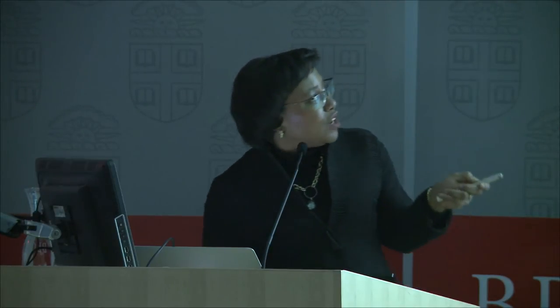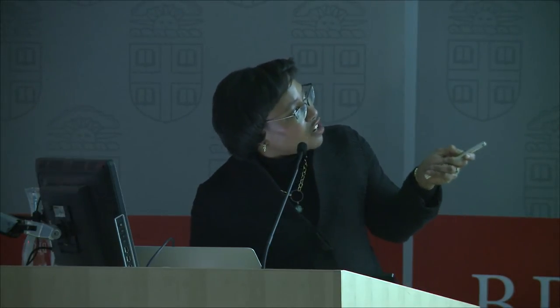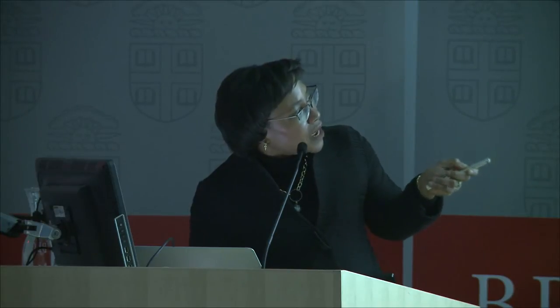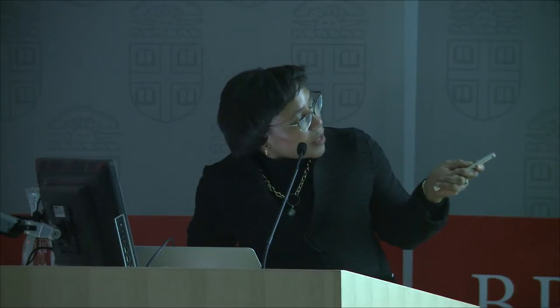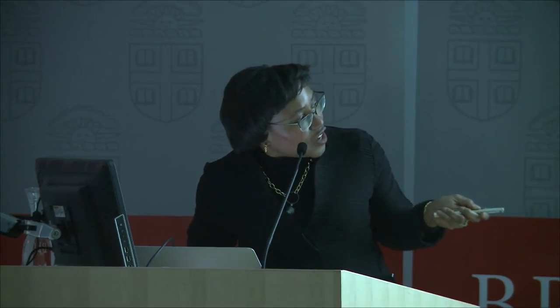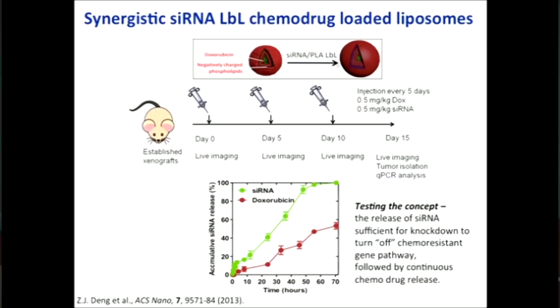So in this recurrent aggressive phase, we look at treatment by introducing siRNA that can actually block that mechanism. And we then deliver the doxorubicin. So the siRNA is released fairly rapidly compared to the doxorubicin, which is released over longer time frames.